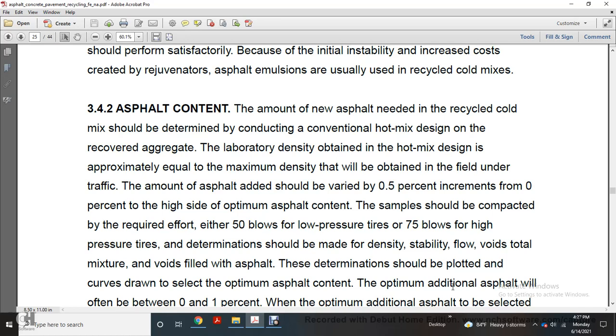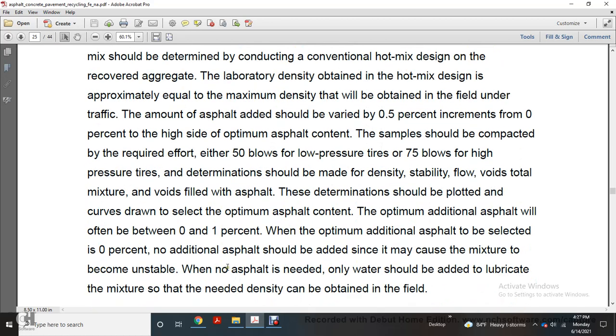On the high side of optimum asphalt content, samples should be compacted with the required effort, either 50 blows with low pressure tires or 75 blows with high pressure tires. Determinations should be made of the stable density, fluid voids, and total mixture voids with the asphalt. The determinations should be plotted as curves to select the optimum asphalt content.